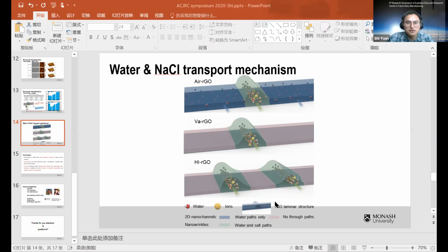But some of the GO membranes have larger water flux, way larger than the ceramic membrane and polymer membrane after certain modification, like the cross-linking by organic compounds. But it depends on the application. If you want to apply the GO membranes for nanofiltration or ultrafiltration, different modification can be used to achieve both high water flux and high rejection of your target molecules.